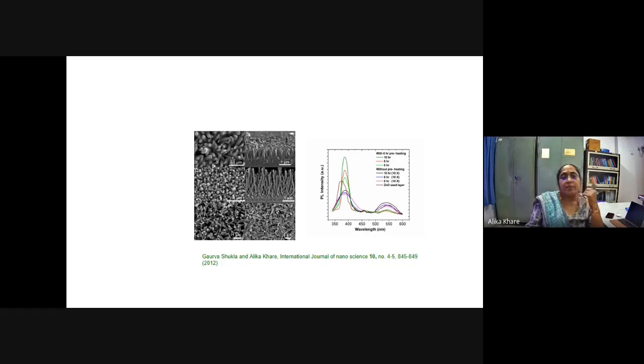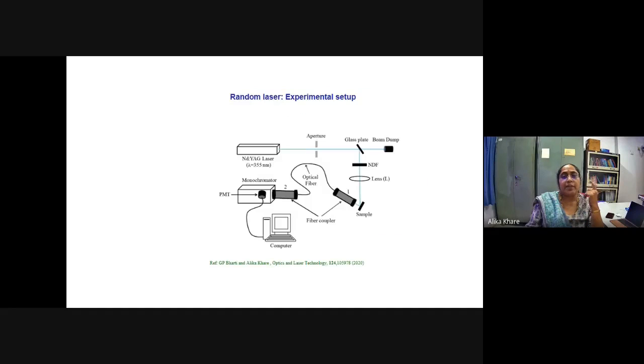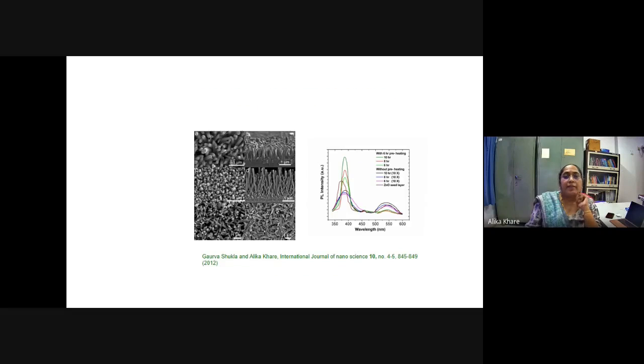So what we did was use the previous experimental setup I described, but instead of using the third harmonic of the Nd:YAG laser, we used its fundamental only. The fundamental is 1.06 micron, or 1064 nanometers, and we excited these rods. Via multiphoton absorption induced emission, we were able to get the band edge emission.